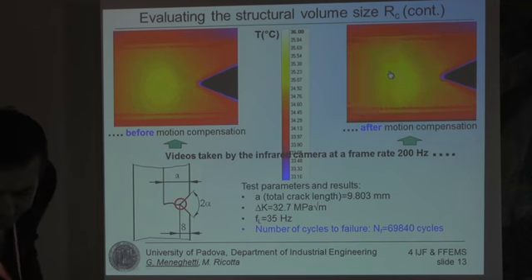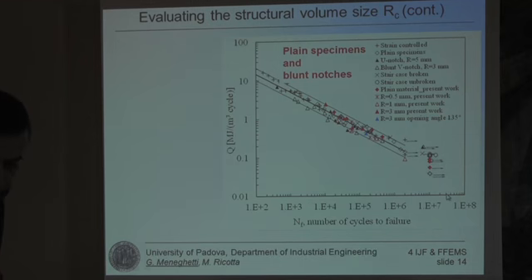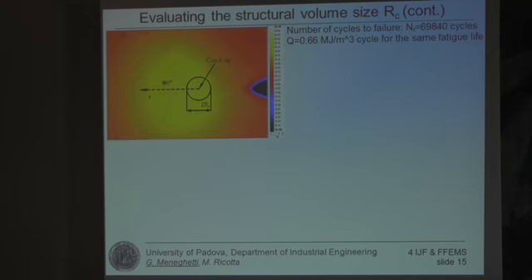Now, if we go back to the characteristic energy-based fatigue curve of this material I have shown you before, and we enter with the fatigue life of our specimen, we come up with a characteristic energy of 0.66 megajoule per cubic meter cycle, and this is the characteristic energy for a given fatigue life.